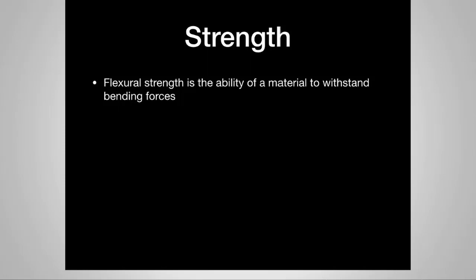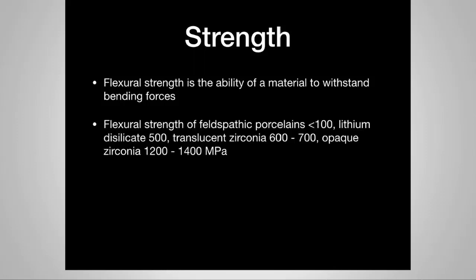Let's talk about how you measure the strength. Flexural strength is the ability of a material to withstand bending forces. We've all seen flexural strength numbers, and that's sort of the number that's in our head when we look at any material. And we're impressed by these big numbers, but I'll kind of give you some ideas here. So flexural strength of feldspathic porcelains. So remember, feldspathic porcelains are basically any porcelain that we've used in the past to cover metal copings, like for a PFM. We have feldspathic veneers that are still being used, but not as much anymore because of their weakness. But you can see that feldspathic porcelains are usually right around 100 MPa.